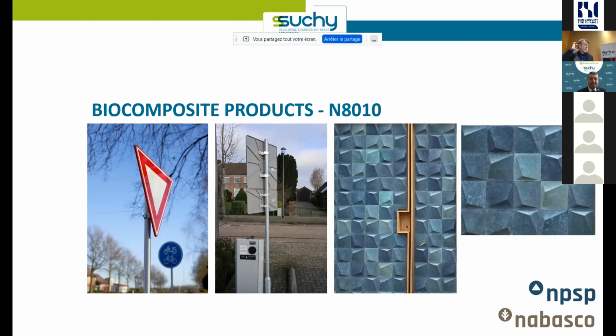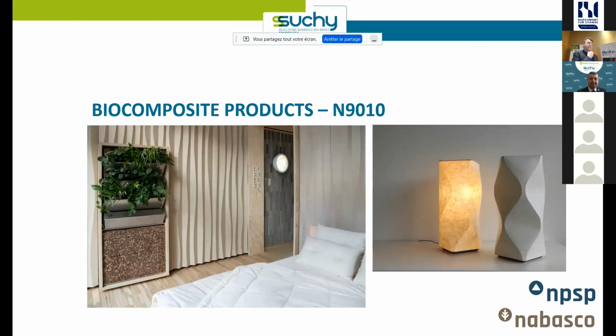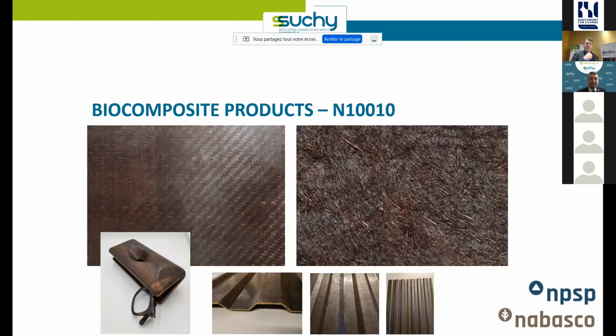For the filler, we use calcite from decarbonation plants of drinking water. And we use short fibers from maintenance of natural areas, so we use reed, for instance. Then we have a thermoplastic material where we combine thermoplastics, PLA and natural fibers. The products you see here are a wall paneling and a lamp, which are both 100% bio-based. So as you can see from these pictures, we really try to go to products.